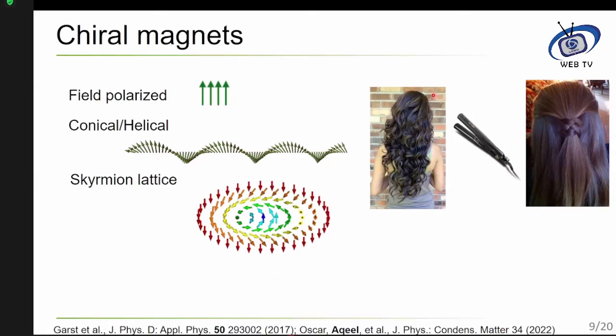If you look at this girl's hair, you can think that the straight hair is just like the field polarized state. Everything is straight, and then there is curly hair. But if you take a straightener, you can gradually make everything straight. There is not a lot of effort. But if you look here, there is a knot in the hair. Whatever you do with the straightener, this knot will not go away very easily. The same holds here. The skyrmion theoretically has an energy minimum, and you cannot go from the skyrmion state to the field polarized state very easily. That's what makes them very special, and that's why they are very famous. They have a lot of similarities with domain walls, but they are robust. They are topologically protected, meaning the topology of this is much different from this.